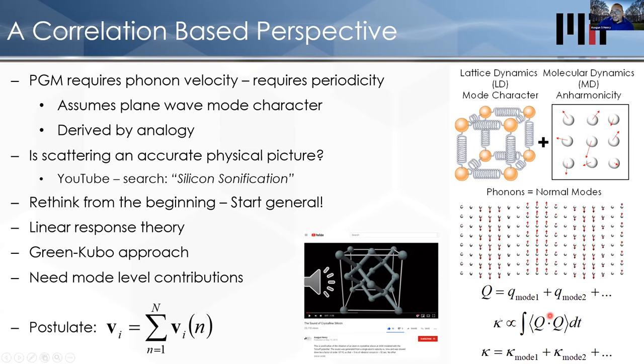And then now what we have is a correlation-based framework where we actually measure how correlated two modes are, and that actually tells us how strongly they contribute to the thermal conductivity. So in this framework, there's no concept of scattering. There's no concept of particles running into anything. All of that's gone. We only have normal modes, and the normal modes interact with each other, and we simply measure how strongly they interact in time. And that way, it's much more general. We can do cases that are extremely disordered or crystalline, fully ordered or disordered, it doesn't matter. Our approach is completely agnostic to what it even is. It could be a molecule, and our theory works all the same way.